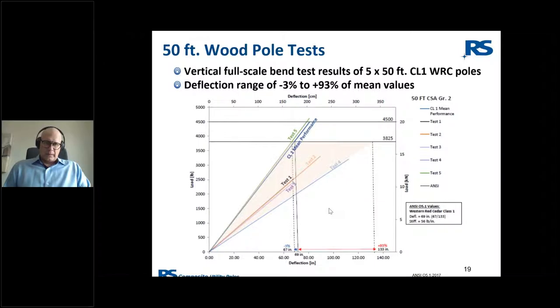So you can see the class one mean performance here, again in the blue, the test five pole very closely followed the class one mean performance graph here. And that's about as close as the mean as you're going to see. Test one, two, three, and four, however, were again far to the right of the mean performance, increasing the deflection, but also falling well short of the class one factored load value.